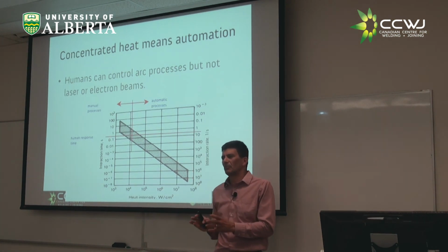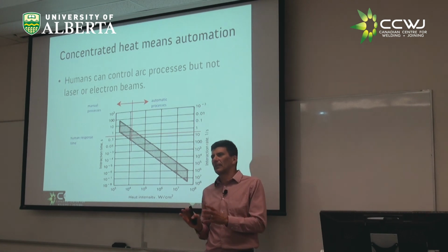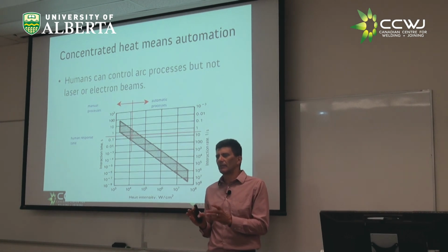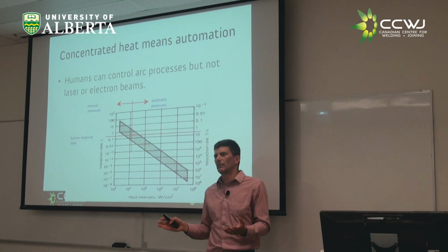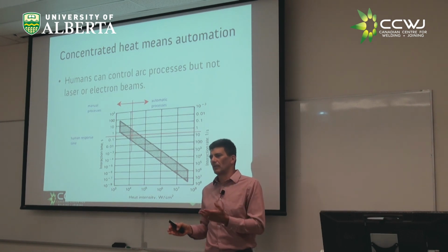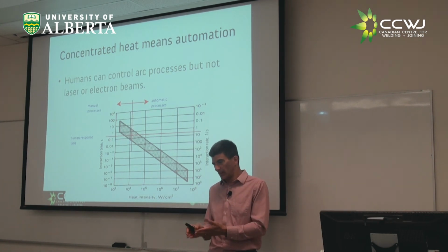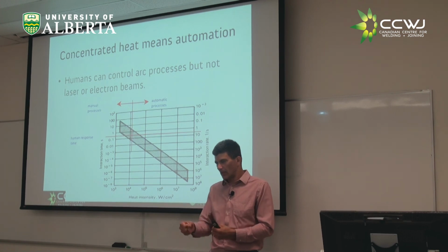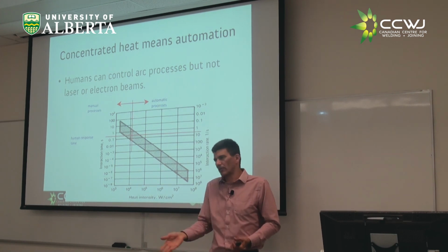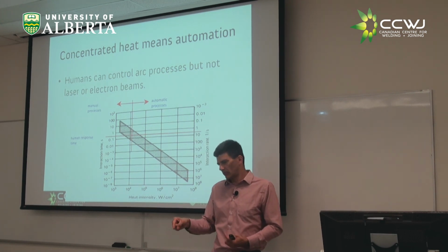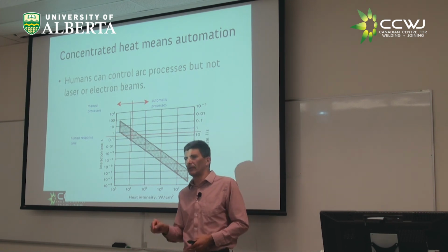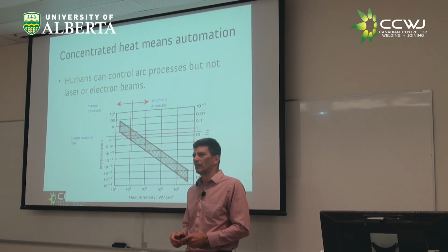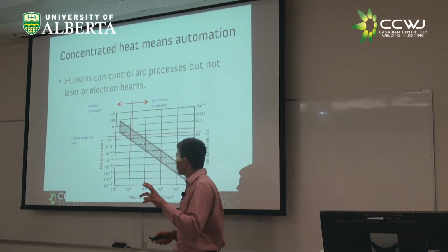This is a super interesting one. The intensity of the heat source also tells you that in some cases you can only have an automated process. Things like a laser, if you spend too much time with the laser stopped, it's like when you're ironing your shirt. If you leave it for too long, you're going to burn your shirt. If you leave the laser for too long, you're going to drill instead of weld. So you have to move. But now, are you good enough to move that fast and still keep on the line? You're not. That's given by the interaction time.